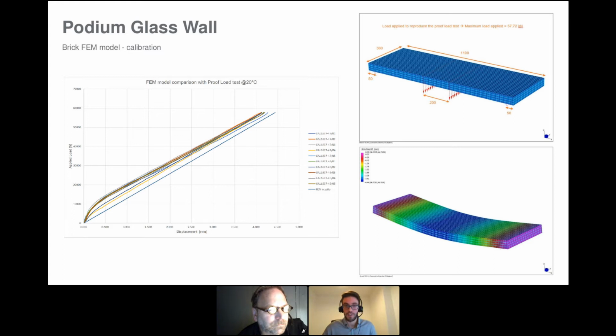And nevertheless, whatever is your results, so even if you get the full composite action, you are limited by a 70% of the effective thickness to be considered. So what we did was kind of using these results also for a different purpose. In order to validate the brick model that we have to generate and analyze after that, we also recreate the setting out of the four-point bending test in the finite element model and test it, analyze it, and compare it with the results of the actual samples analyzed in the test lab.